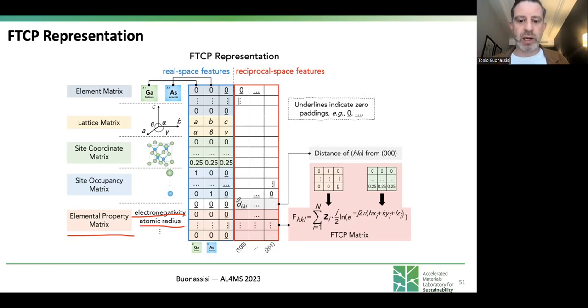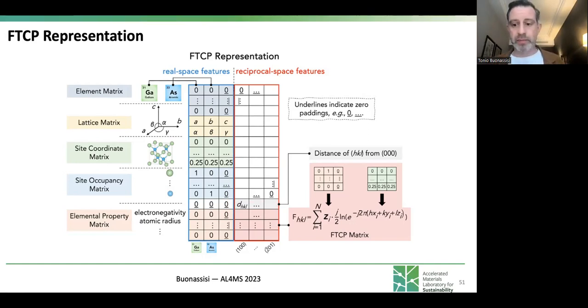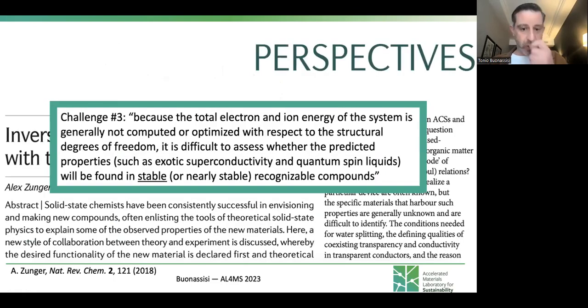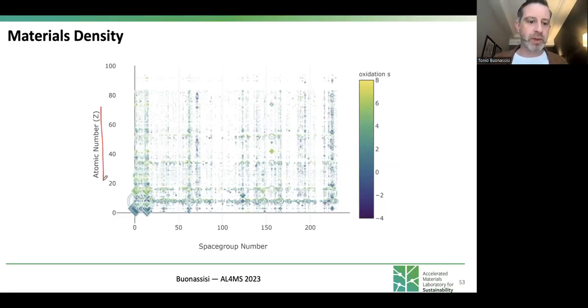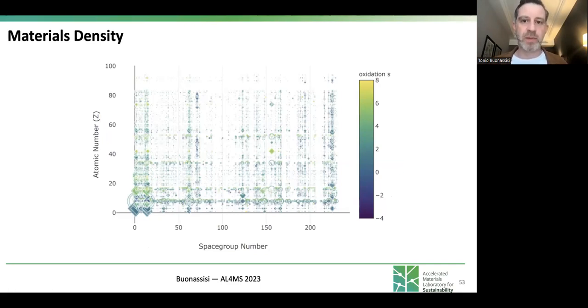You can almost think of this as a bitmap representation of a material going into the algorithm, which then compresses that information. You have to deal with training imbalance. Training the algorithm using Materials Project — viewed as a function of atomic number on the y-axis and space groups on the x-axis — there's a lot of blank space, not necessarily because those compounds don't exist, but because research grants focused on areas like lithium-ion batteries, leaving the lithium-aluminum phase diagram very well calculated but big gaps elsewhere.